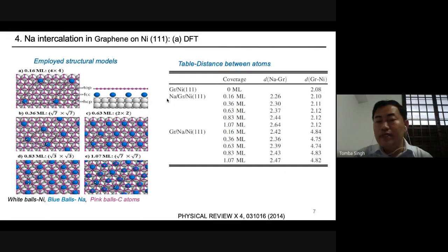If the sodium layer is floating above the graphene, then with the increase of the coverage, we see an increase of the distance between sodium and the graphene. Why does the distance increase as the coverage increases? The sodium crystals are covering above the graphene. If we introduce more sodium atoms, the crystal becomes better. That's why the interaction between the graphene and this floating adsorbed sodium layer decreases, and the distance increases. And the graphene-nickel distance is not changing much.